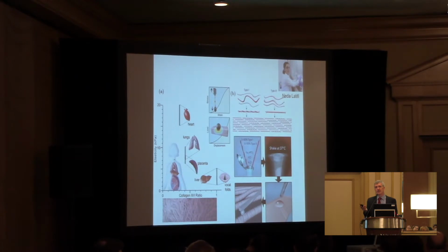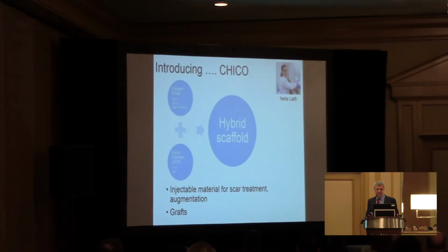You will find heterotypic collagen 1 and 3 fibers in the human body, but we can do it chemically as well, so that our fibers have a little bit of the properties of collagen 1 and collagen 3. We did collagen 1, collagen 3, and different mixtures of the two. We tested the mechanical properties and so on before finding that the 50-50 combination is probably ideal.